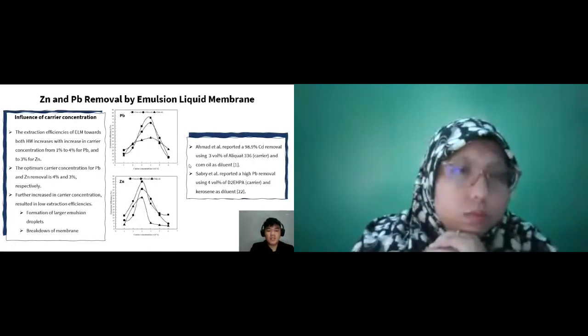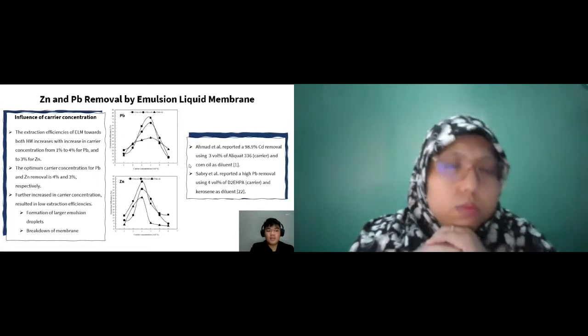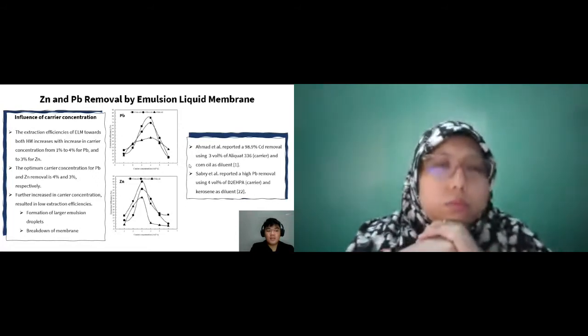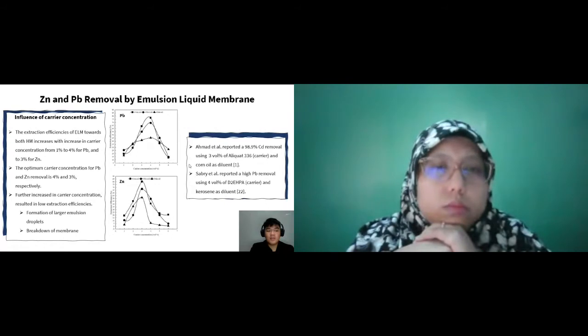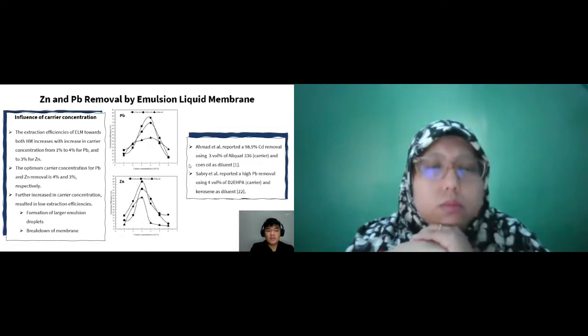Ahmad et al. have reported a 98.9% cadmium removal at a carrier concentration of 3 volume% using Aliquat 336 as the carrier and corn oil as diluent. Meanwhile, Sabry et al. reported a 4 volume% carrier concentration, with D2EHPA as the carrier and kerosene as the diluent.